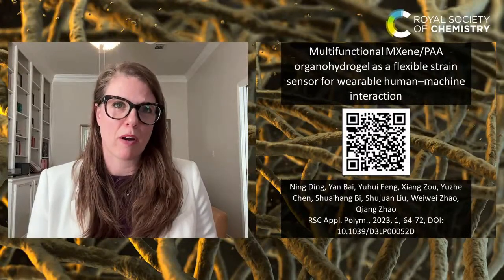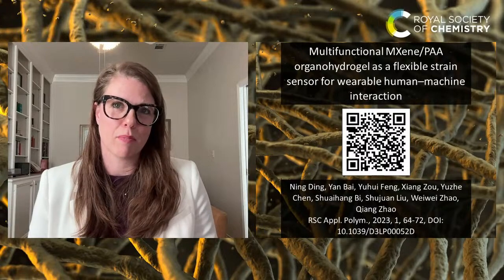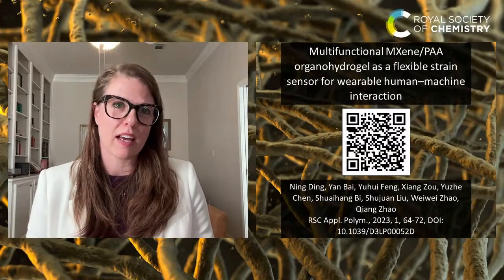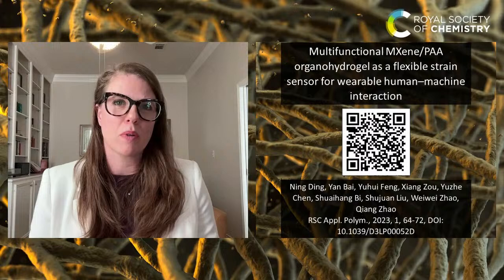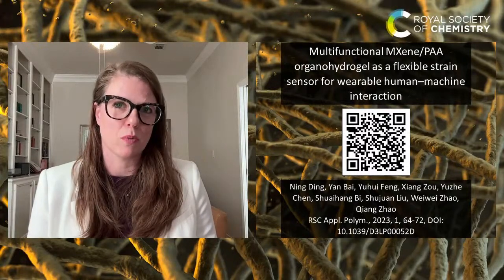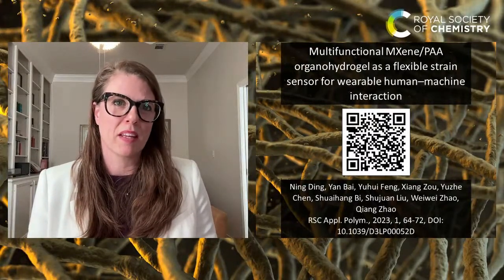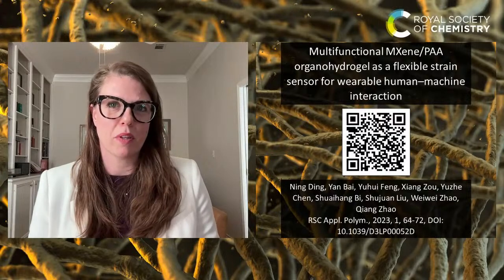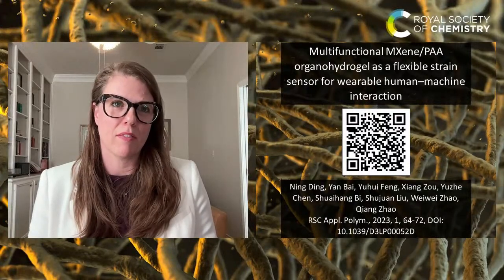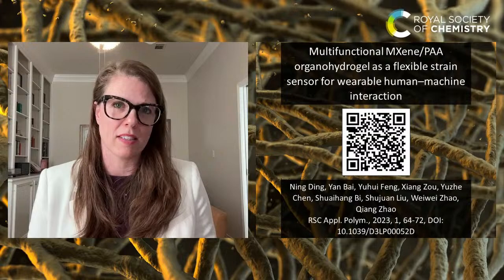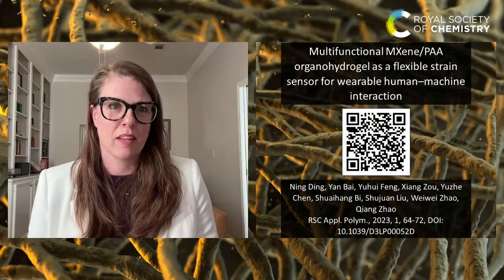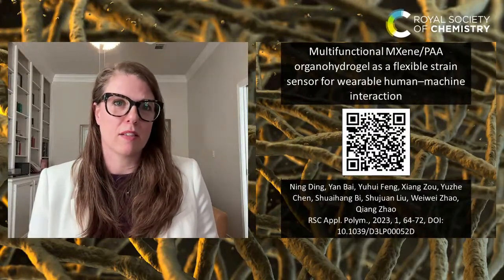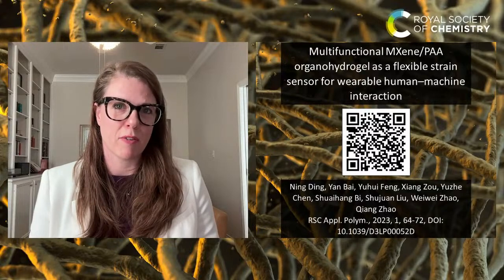Here, the authors prepared conductive organohydrogels by the in situ polymerization of acrylic acid and a crosslinker in an aqueous solution of MXene nanosheets, which are transition metal carbides. They then partially replaced the water with glycerol and examined the impact of the percent of replacement on performance and found a Goldilocks effect. The organohydrogel has excellent mechanical resilience to deformation.